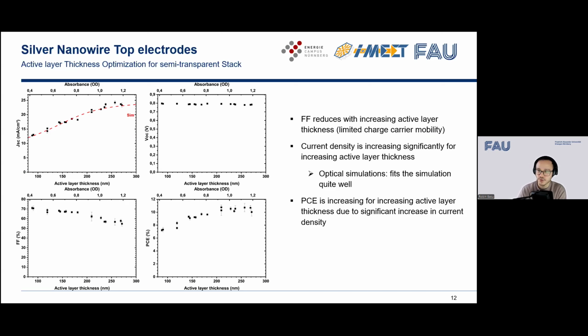So to counteract the effect of current density losses, we have to increase the active layer thickness in order to absorb more photons again and increase our JSC. And that's actually a quite nice trend that you can also see. And again, we fitted it to our model in the optical simulations. And as you can see, it fits again quite well.